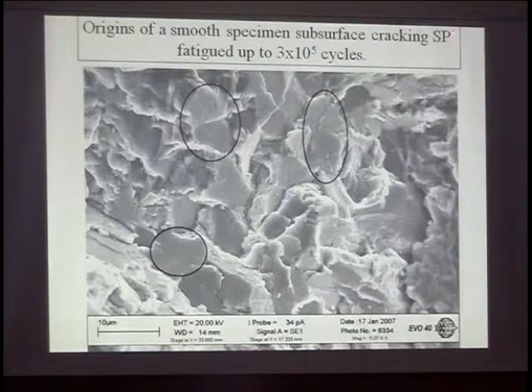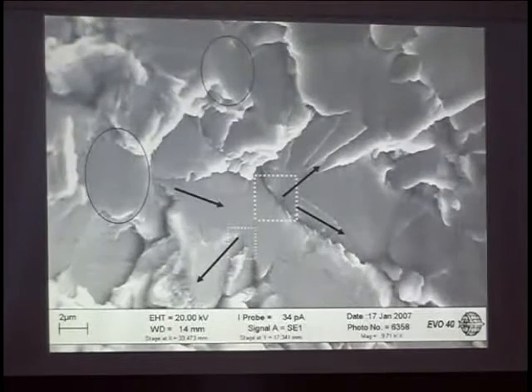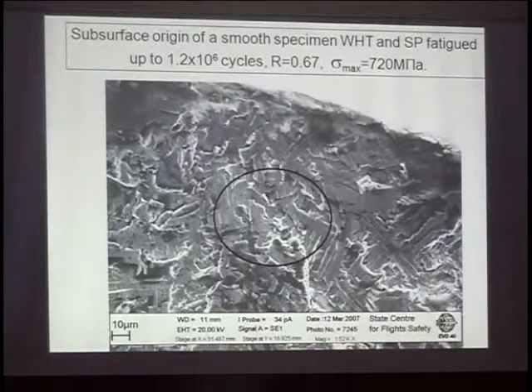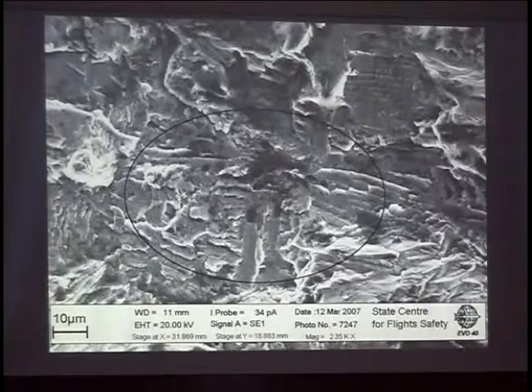The same can be seen for another situation, only shot peening. Also we can see the first facet. Out of there we can see very good, strongly expressed evidence of material cracking out of this area. For instance, this is the place of the first smooth facet, and then you can see clearly announced material cracking in different directions around. The situation for the faceted pattern is not very clear because of the lamellar structure, but if we look at high magnification, we can also see an area with a very, very clear smooth facet from which the start of material cracking can be seen.